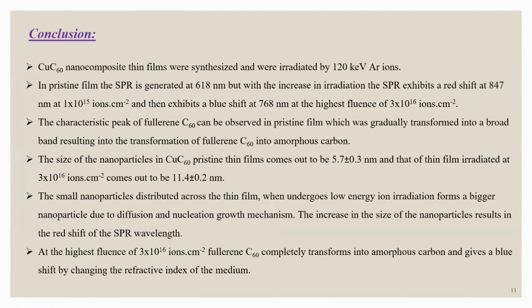Conclusion: CuC60 nanocomposite thin film was synthesized and irradiated with 120 keV Ar ions. We have seen an SPR peak at 618 nanometers for pristine, which was red shifted to 847 nanometers at 1E15, and then exhibits a blue shift at 768 nanometers at the highest fluence of 3E16 ions per centimeter square. The characteristic peaks of fullerene C60 observed in pristine were gradually transformed into a broad band, resulting in the transformation of fullerene C60 into amorphous carbon. The size of the nanoparticles increased from 5 nanometers to 11 nanometers.